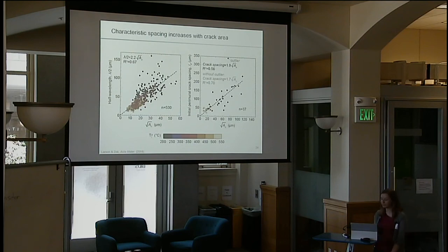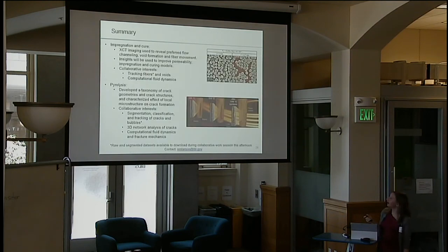So in summary, we've looked at in-situ XCT experiments from impregnation and cure, where we looked at fiber movement and preferred flow channeling, and have been able to develop some insights that will help us improve permeability, impregnation, and curing models. And some collaborative interests that I have for the future would be to track the fibers in the voids and do CFD in these fiber beds to understand the fiber movement and bubble formation.